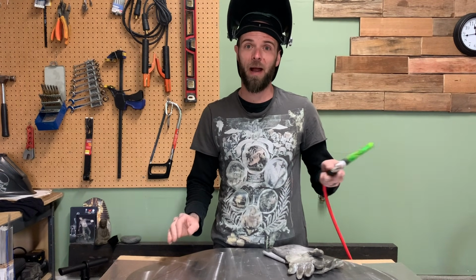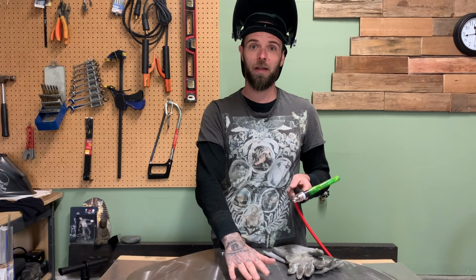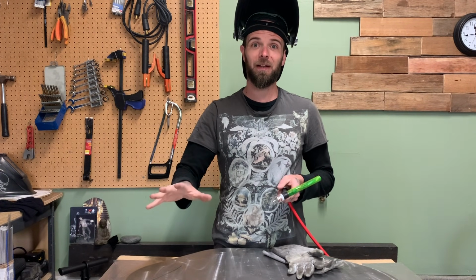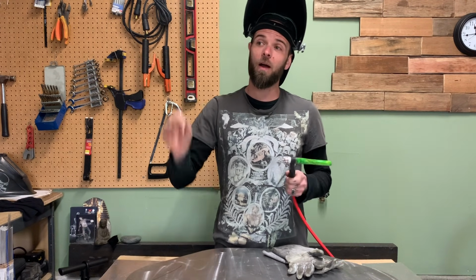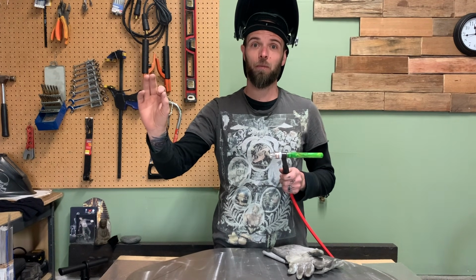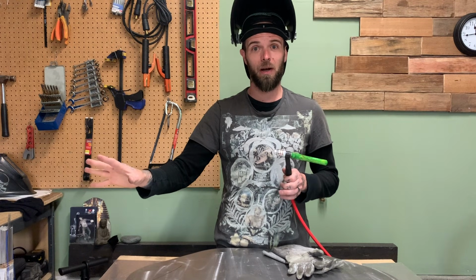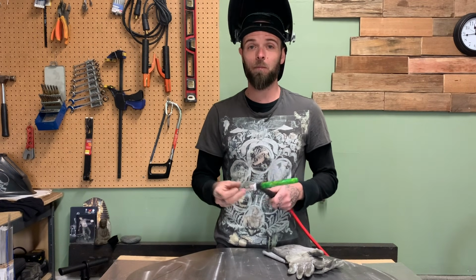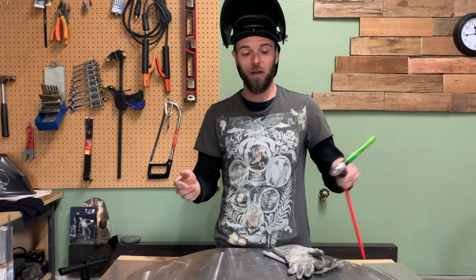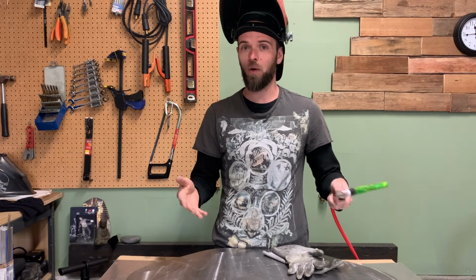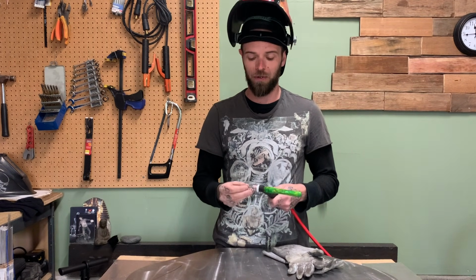Let's just run a couple passes on some scrap material like I've got here. We're going to make sure it's running nice and clean, nice and shiny, and then once we're confident that our torch is set up really well, our gas CFH level is set up really well, everything else with the machine is set up quite well, our post flow is still buzzing away when we're done, we'll add filler rod to the mix then. But for now, let's just start with a couple passes running without fill, autogenous welding or dry welding. Dry arcs is what I call it sometimes with my students. But yeah, let's keep it simple, let's start with that.